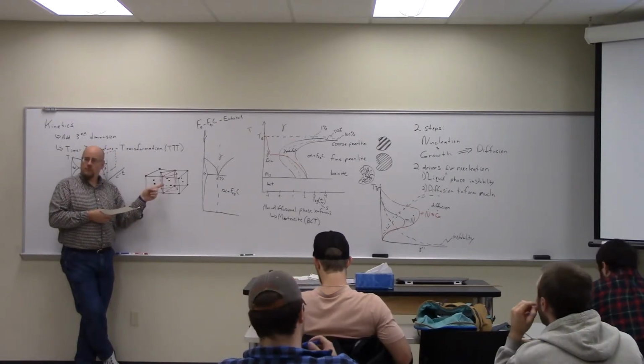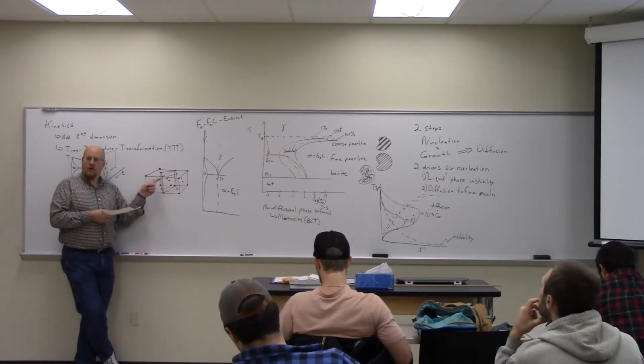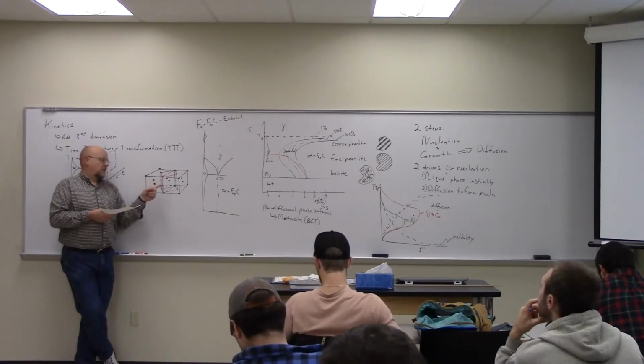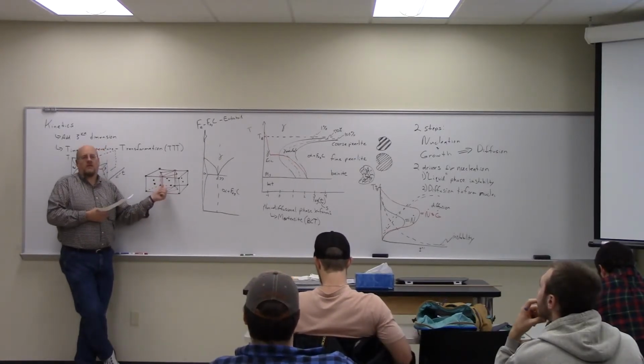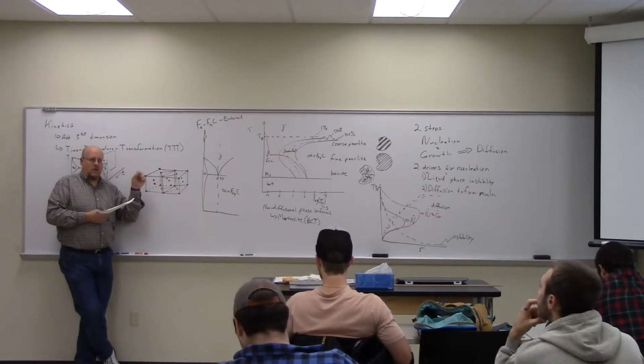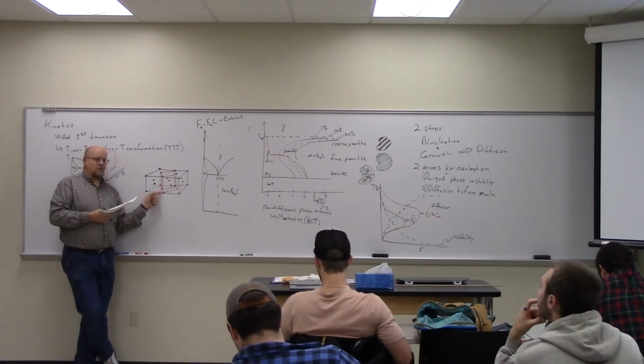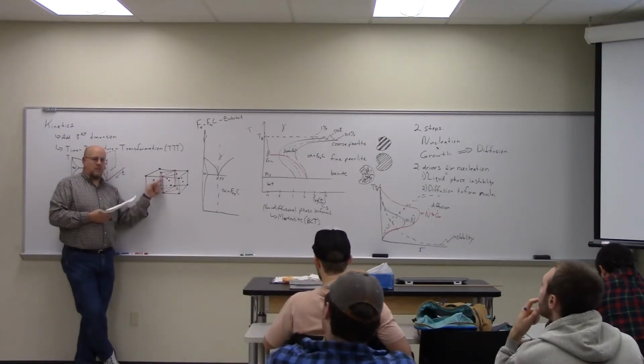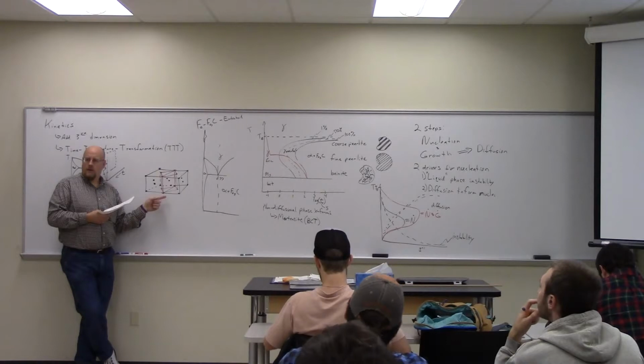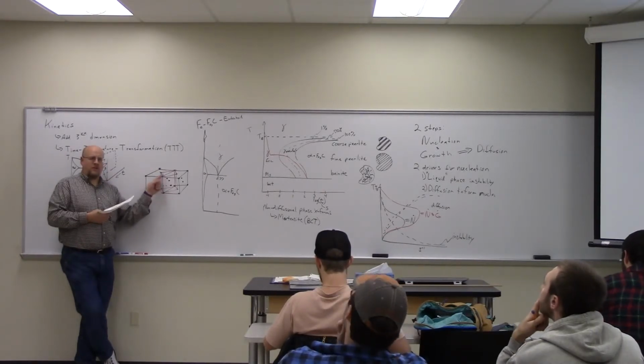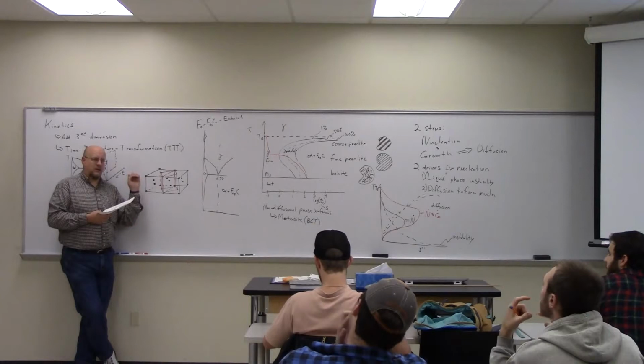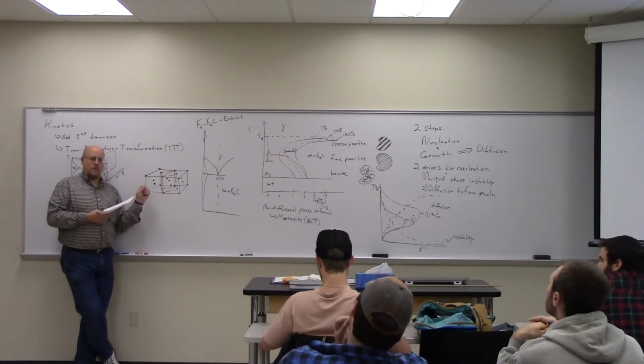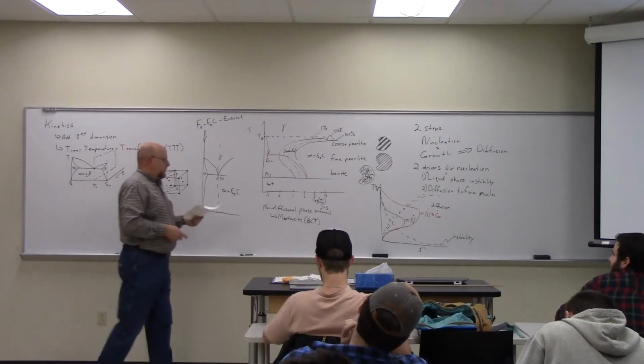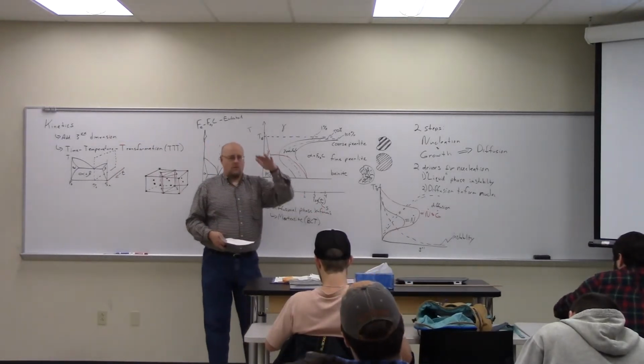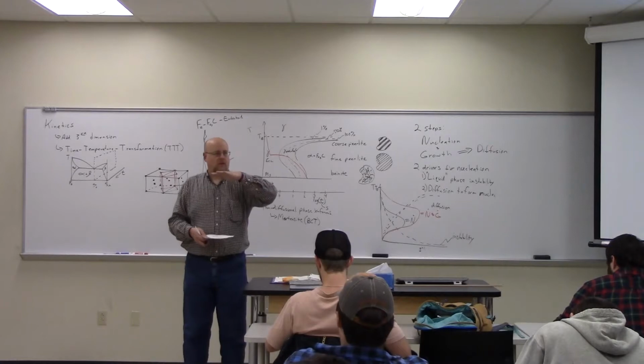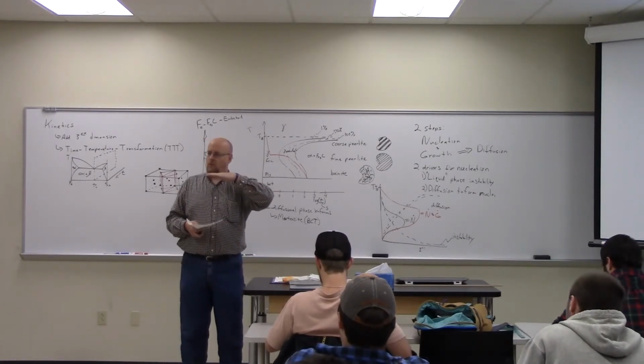Everybody kind of see that? How a body center diagonal could come from this? So basically what that means is FCC is like a body-centered tetragonal, but with the special condition that the A of the body-centered tetragonal is equal to the C divided by the square root of 2. If that C changes ever so slightly, it's no longer FCC, it's just body-centered tetragonal. Okay? So that's how it can happen rapidly. There's just enough cooling pressure to get it to shrink, and then you have a new crystal structure.